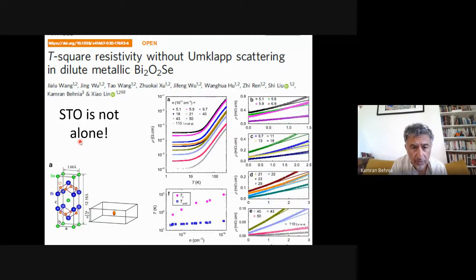But what I wanted to show here is that afterwards, Xiaolin, who went back to Hangzhou, also discovered that T-square resistivity exists in another system, which has a very different phonon spectrum, bismuth oxyselenide. This is the crystal structure, and again, the Fermi surface is very small, single component. And if you look at this behavior, you see the result is not very different from what we saw in STO. And this brings us back: we should find a way to understand T-square resistivity.